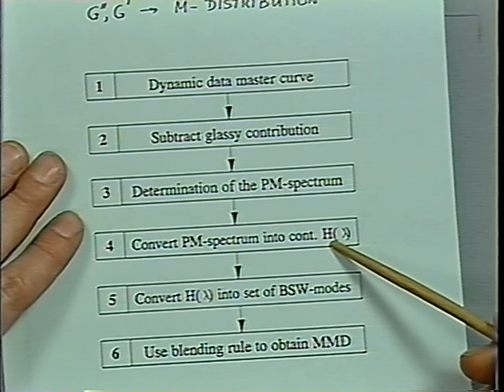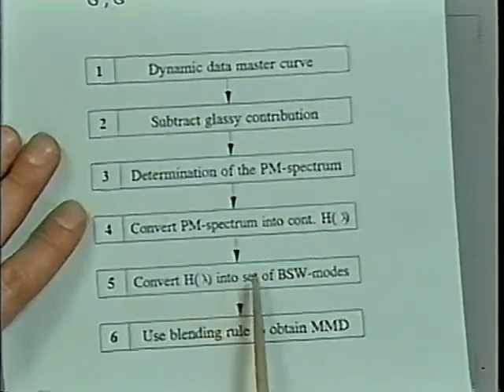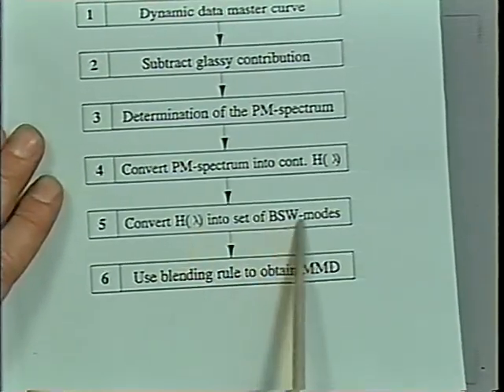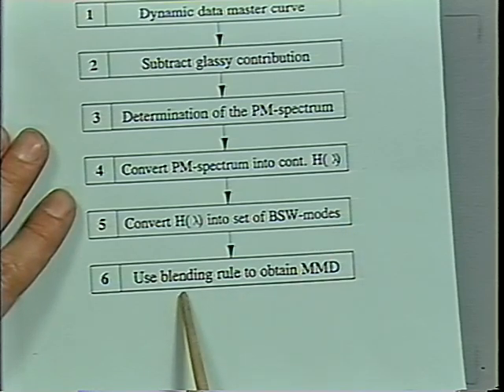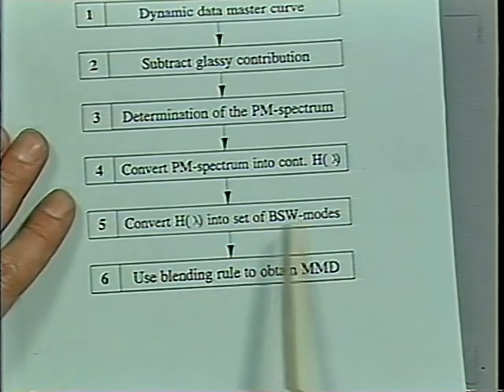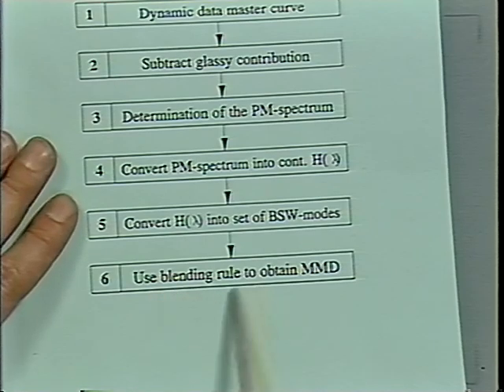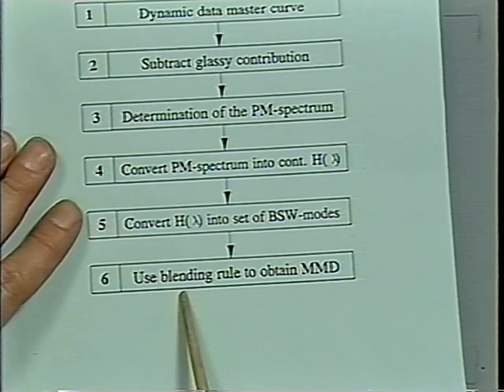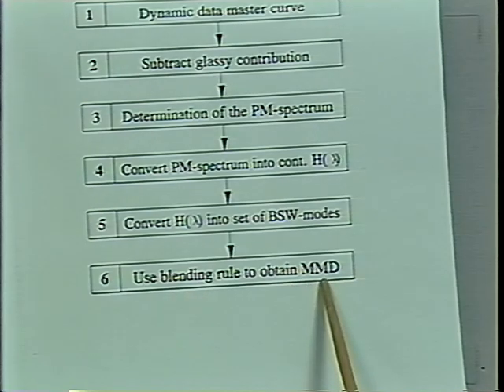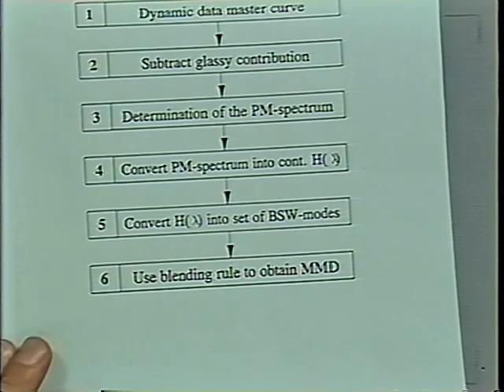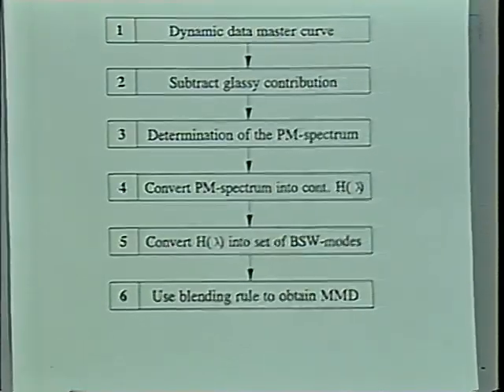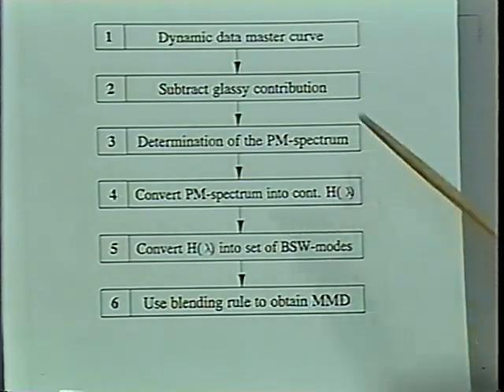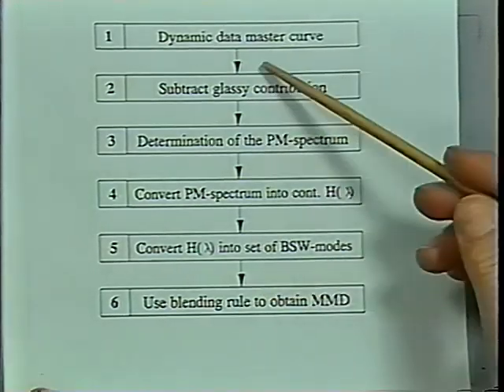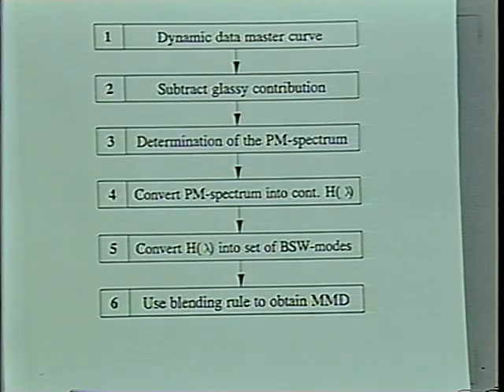Now, this H spectrum can be described by a set of BSW modes, and from the set of BSW modes, we get a set of monodispersed fractions and their weight fractions. We get their molecular weights and their weight fractions. And then we have a discrete molecular weight distribution and can maybe convert this into a continuous distribution, something like that. So there is hope that we can pursue that objective.